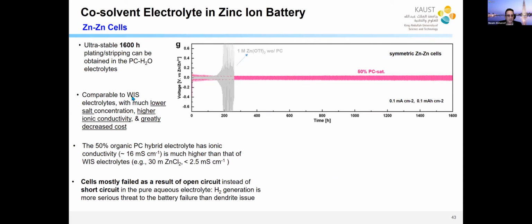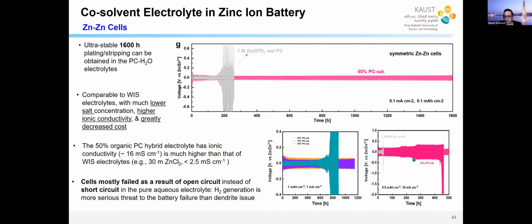And what's neat about this solution is that we have a concentration of about 2 molar. Water-in-salt electrolytes use 15, 20 molar. It means you have to put in a lot of salt, which is expensive. And on top of that, it kills the conductivity. So our conductivity here is 16 millisiemens per centimeter. But for a 30 molar salt in water-in-salt electrolyte, it is only 2.5. So this has an advantage in conductivity and an advantage in cost. You can go to higher currents, and you can still see the PC-containing solvent is best.